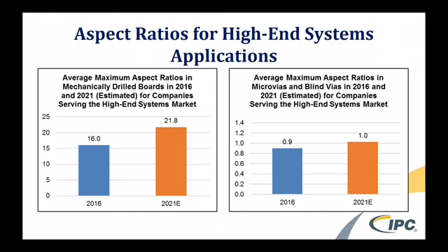And again, this is an average, but when they say a 1.0 aspect ratio for blind vias, you're talking, say, a 3 mil blind via, 3 mils deep. But we also expect that some companies will be doing 2.5 mil blind vias and maybe potentially 3.5 mils deep, which will knock that aspect ratio up to about 1.3. And you'll also see some plated through holes, as you see on the left here, well above 21.8 to 1. Again, this is going to put additional pressure on not just via formation and high quality drilling, but also going to put some pressure on us from a plating standpoint, how we metallize these holes and these vias.